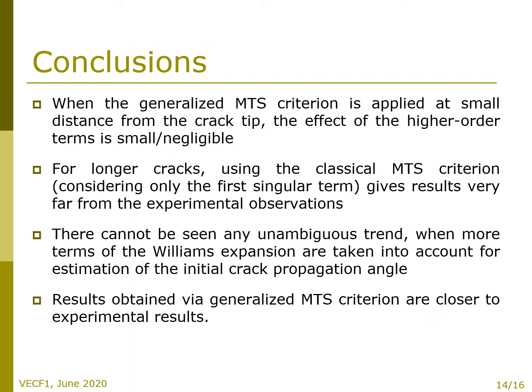Based on the results presented in the previous two slides, the following conclusions can be stated. When the generalized MTS criterion is applied at small distance from the crack tip, R_C, it means critical distance, equal to 0.1 or 0.5 millimeters, the effect of the higher order terms is small or negligible. For longer cracks, using the classical MTS criterion, considering only the first singular term, or what was the orange curve in the plot, gives results very far from the experimental observation.